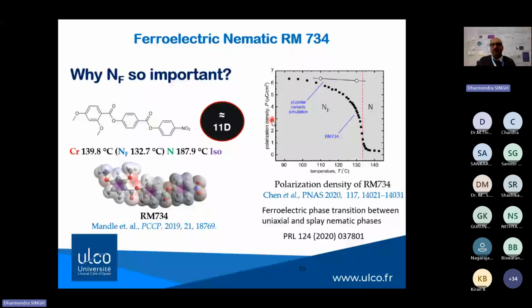This is the molecular structure of RM734, and you could see here that the spontaneous polarization is around 6 microcoulomb per centimeter square, and this polarization changes when this material changes from ferroelectric nematic to nematic transition.